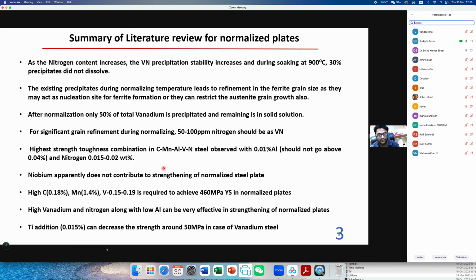After this requirement, we studied the literature. These are the summary of the literature. David also suggested some literature, which was very beneficial. With increasing nitrogen content, most of the literature suggests that vanadium nitride precipitation stability increases, and during soaking at 900 degrees, some papers suggest that 30% of the precipitate will not dissolve, and the existing precipitate during normalizing leads to refinement. They can act as nucleation sites and also restrict the austenite grain size.